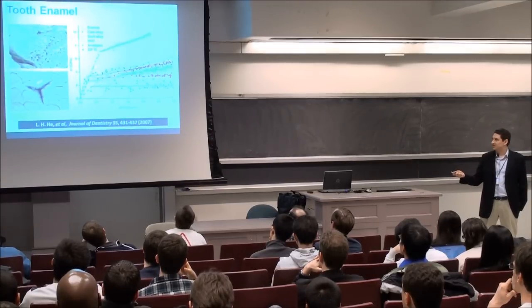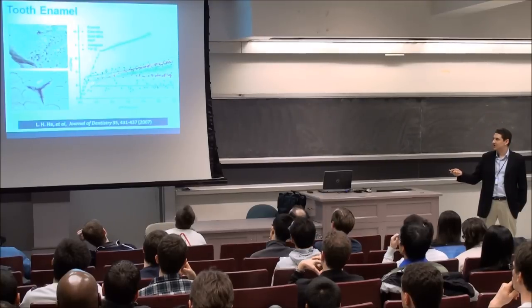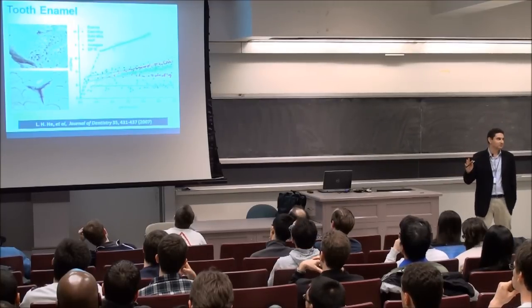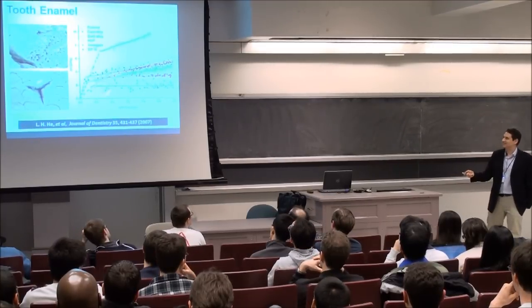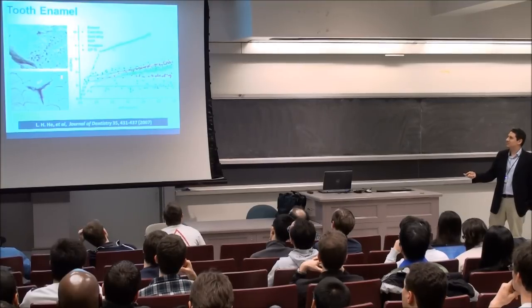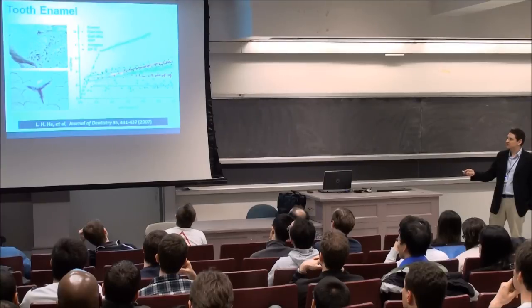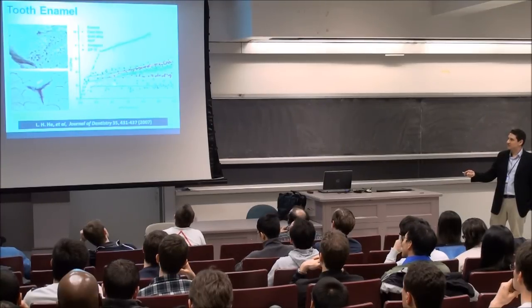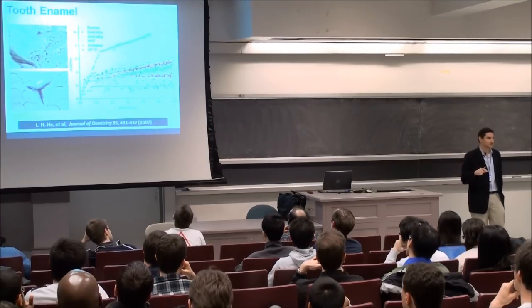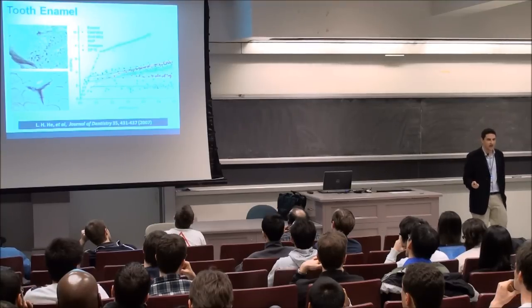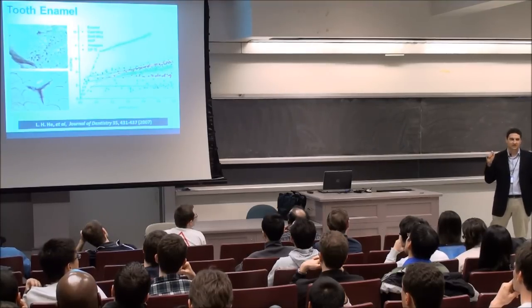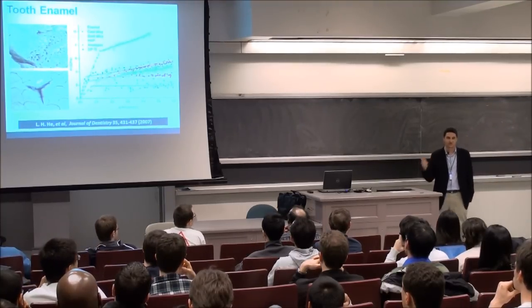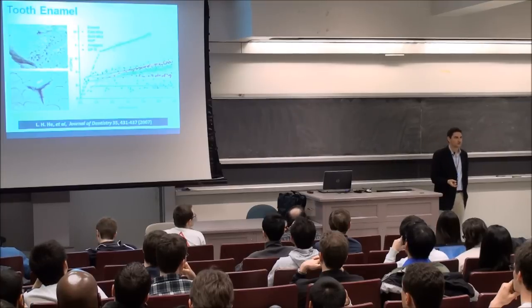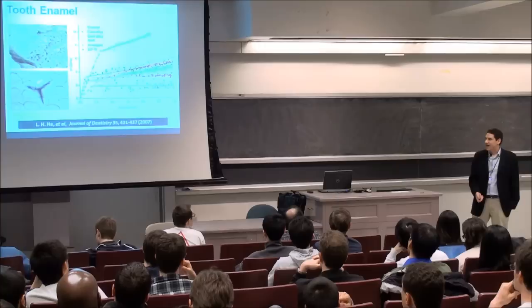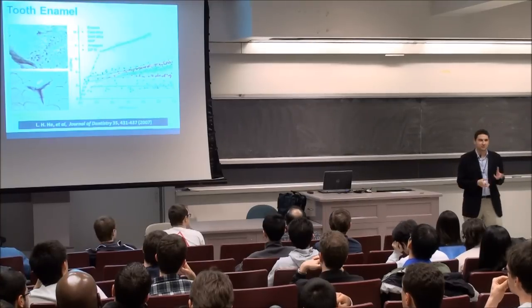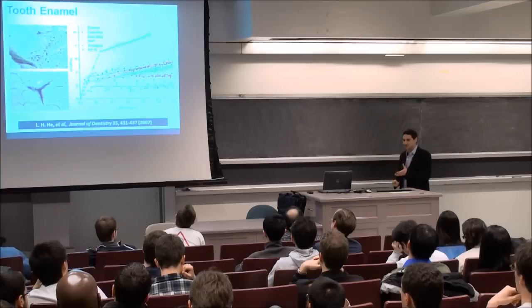It doesn't fracture the way that, you can see this is the stress strain curve for hydroxyapatite. I'm in a mechanical engineering department, so I learned to love these things. But basically, if you look at the actual tooth stress strain curve here, you can see it's a tougher material. It doesn't fracture the way that hydroxyapatite does. And of course, the reason for that is because tooth isn't just hydroxyapatite, it also contains proteins. And these proteins confer some toughness on the tooth. And basically, you have this rugged surface, which is a biomaterial. And so it's an interesting surface to work with.